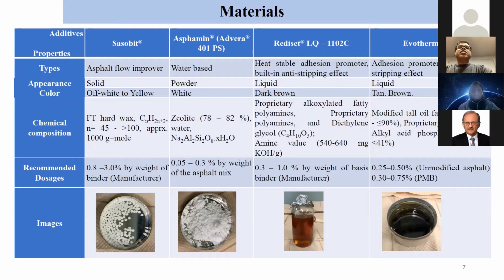And these are the recommended doses. Sasobit is 0.8 to 3% by weight of the binder. And then Advera is 0.05 to 0.3%, so that is by the weight of the mixture. That is different from by weight of the binder. But the other two, Rediset and Evotherm, are by the weight of the binder. So Rediset recommended is 0.3 to 1%, and Evotherm is 0.25 to 0.5%.